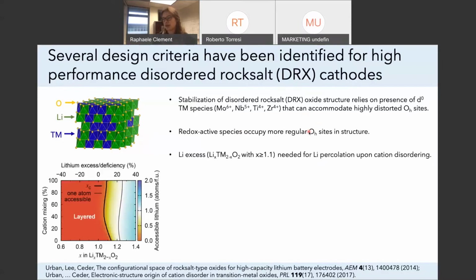Another important design criterion is the amount of lithium that we have in the material. And lithium excess is needed in these particular materials to allow for good lithium percolation. What that means is long-range lithium diffusion relies on the connection between lithium sites here that are percolating through the structure. And for this to happen, we need some excess lithium.